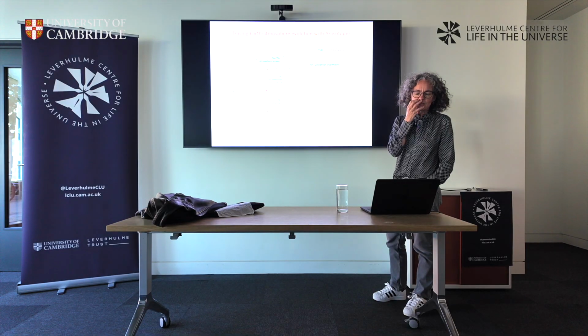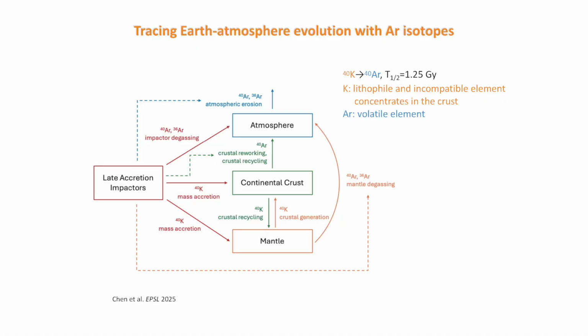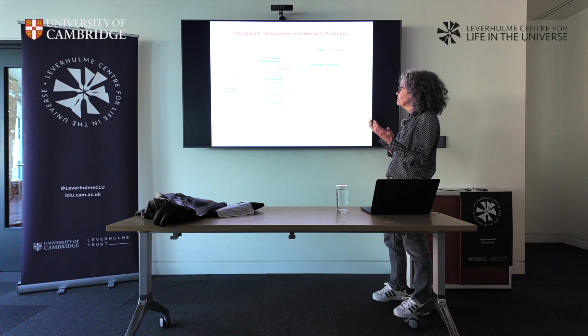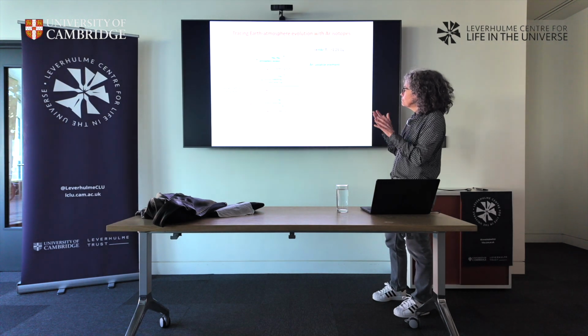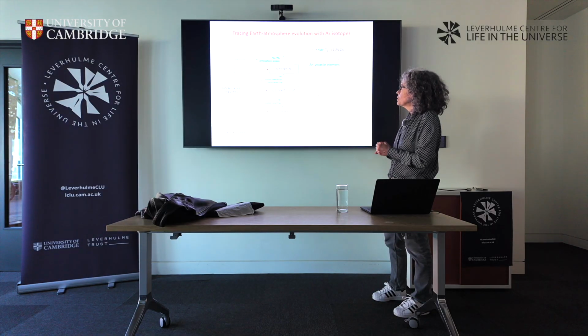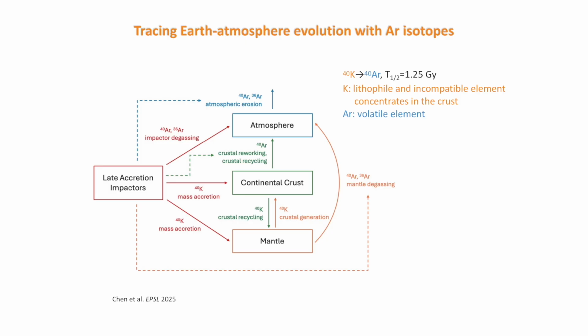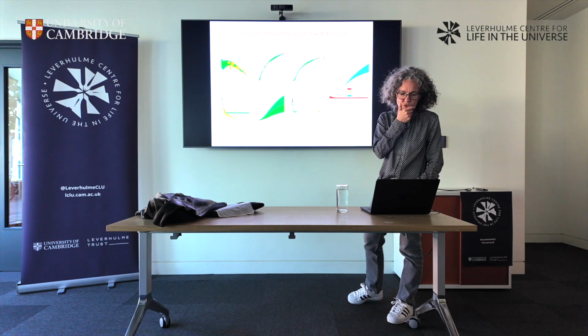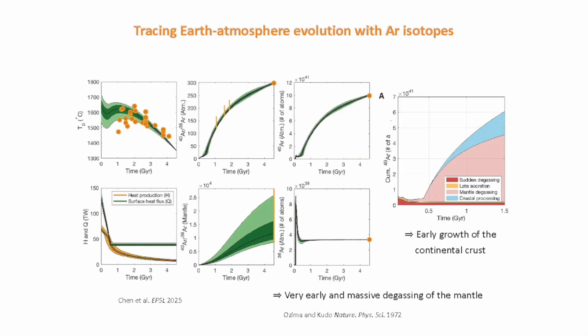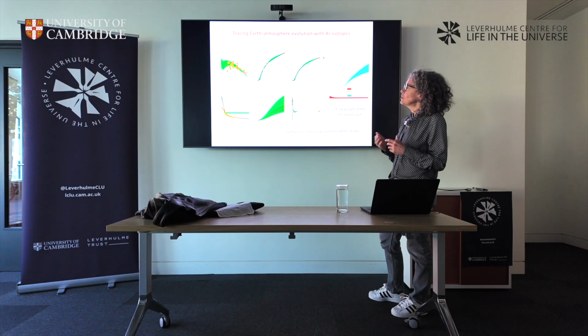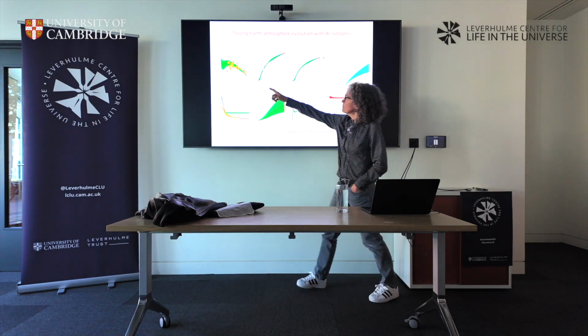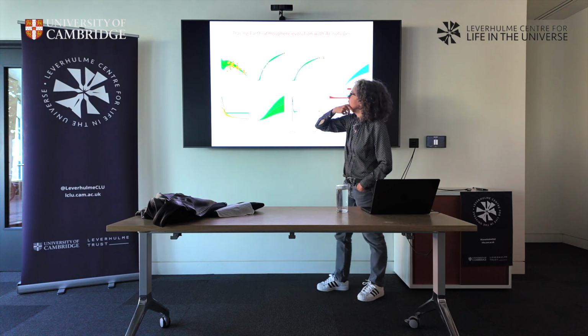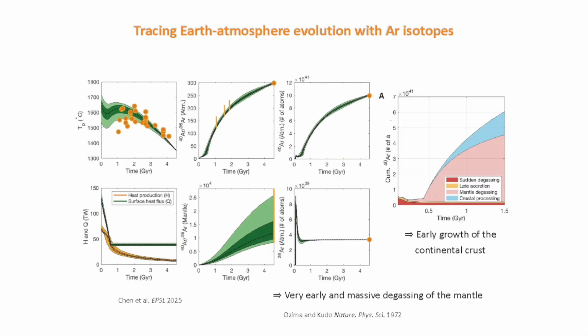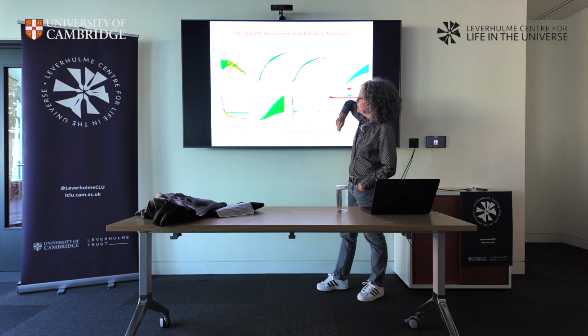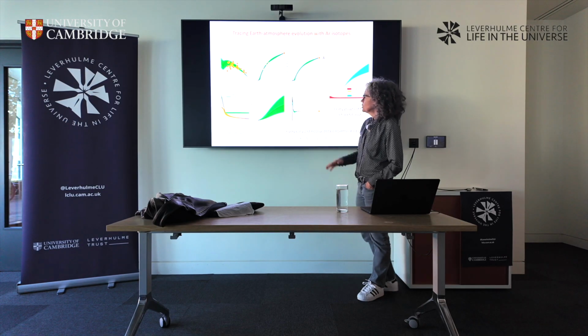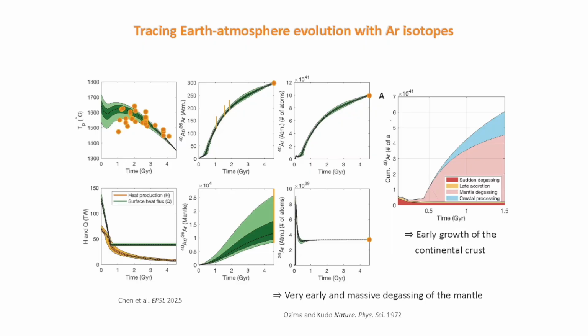So coming back to noble gases tracing Earth's atmosphere evolution, argon isotopes are also widely used because argon is assumed to be a volatile element degassing to the atmosphere. So you can come up with models of atmosphere formation, but also you can constrain continental crust formation. I'm showing you just one of the most recent models, by Chen et al. last year, trying to be consistent with the mantle dynamic evolution models. So the cooling of the mantle over time, which is the orange data set, trying to fit the present-day 40argon content in the atmosphere, 36argon in the atmosphere, and the 40-36 argon ratio in the mantle, and also trying to fit these 3 points, which is actually just one.